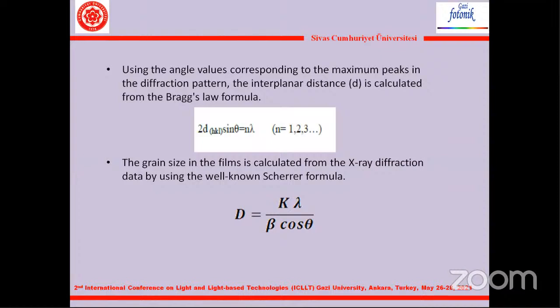Using the angle values corresponding to the maximum peaks in the diffraction pattern, the interplanar distance is calculated from Bragg's law formula. In the equation, n is the order of reflection, lambda is the wavelength of the incident beam, d_hkl is the distance between planes, and theta is the reflection angle of the beam with the plane. In the calculations, lambda was taken as 0.154 nanometers.